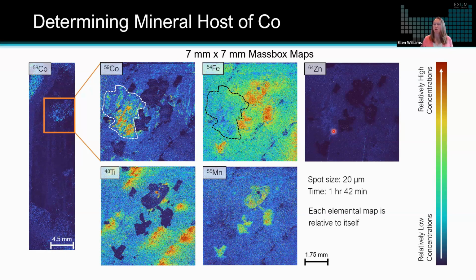But where this technique really adds value compared to some of the other techniques is with something like zinc. So zinc is a trace element. You can see that the picture is relatively blue, it's a relatively low concentration of zinc everywhere on the sample. Zinc is in the parts per million level. So likely might have been below the detection limits of other techniques that might have been used to look at just the bulk elements and determine the mineralogy.